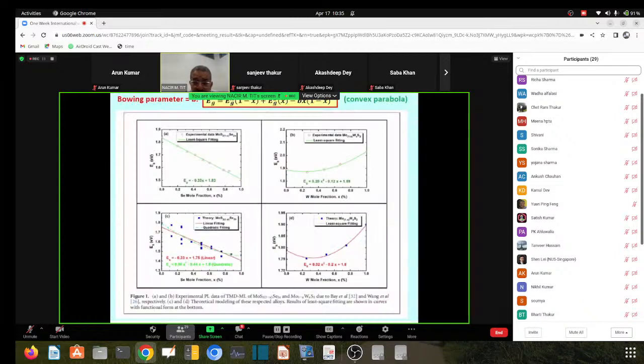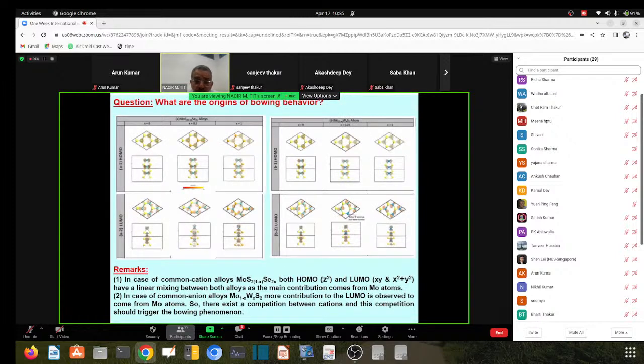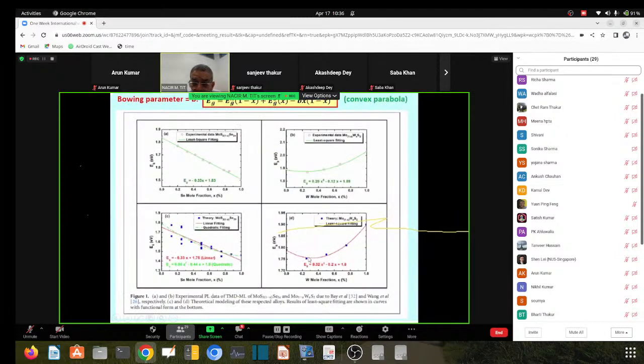Now to investigate what is the cause of the bowing, we did further investigation. So basically, we started with the HOMO-LUMO eigenstates. On the left side, it shows the common cation alloy, from x equal to 0 to x equal to 1. And by the way, the minimum of the parabola is about 0.25. Whereas here it's linear, so it does not matter. So we take x equal to 0, x equal to 1, and x equal to 0.5.